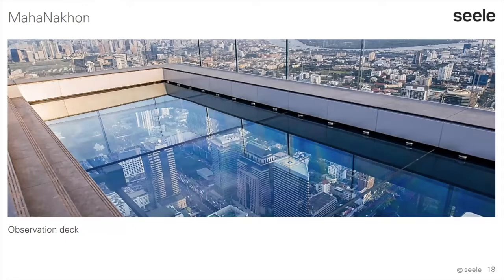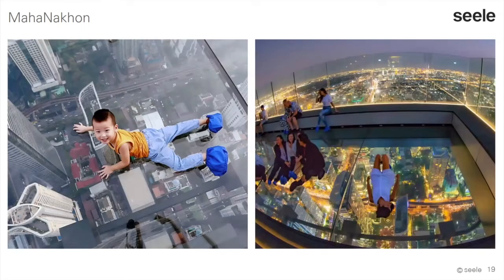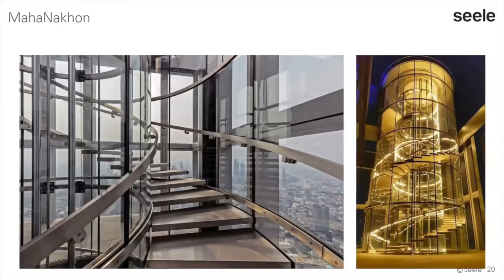Here you see the result. Then after the edges of the glass were cladded, and you can see people have quite a lot of fun there, by day, by night. And now let's have a quick look into the glass cylinder. So this glass cylinder here is a double glass cylinder, an inner and an outer one. And in between the inner and the outer one, we have a spiral staircase, as you can see it here. This staircase, and in the center of the inner cylinder, we have an elevator. So with this elevator or staircase, you go up to the rooftop level where you then reach the observation platform.